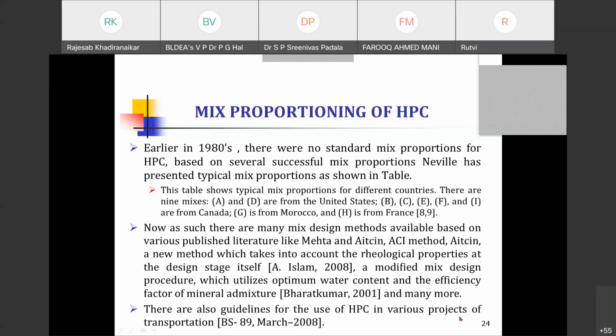And now, of course, some mix design methods are available for us based on various published literature, a very popular one being Mehta and Aitcin. The ACI method is also there. ACI is basically for high strength concrete, and you can extend it; ACI 363 we have as a code. So you can extend it for high performance concrete also. And Aitcin has refined his own method that takes into account the rheological properties of the mix design also. And then a modified mix design procedure is also there. The LCPC method is also there. And this modified mix design procedure utilizes optimum water content and the efficiency factor of mineral admixtures.